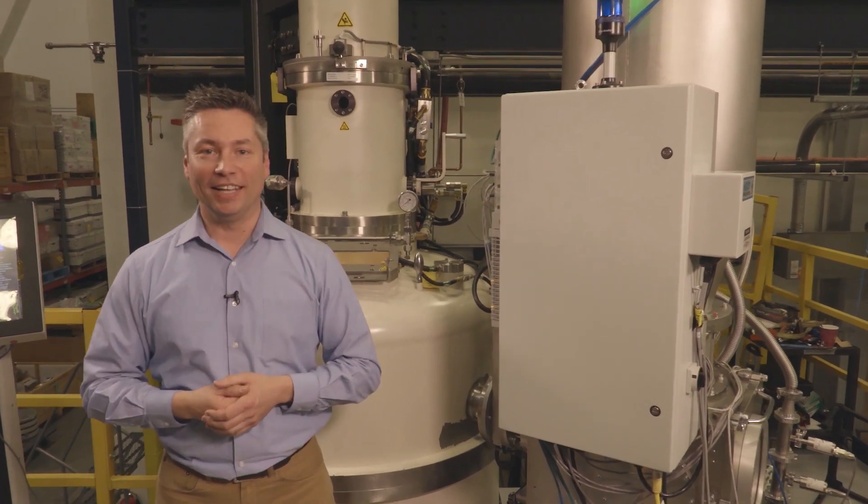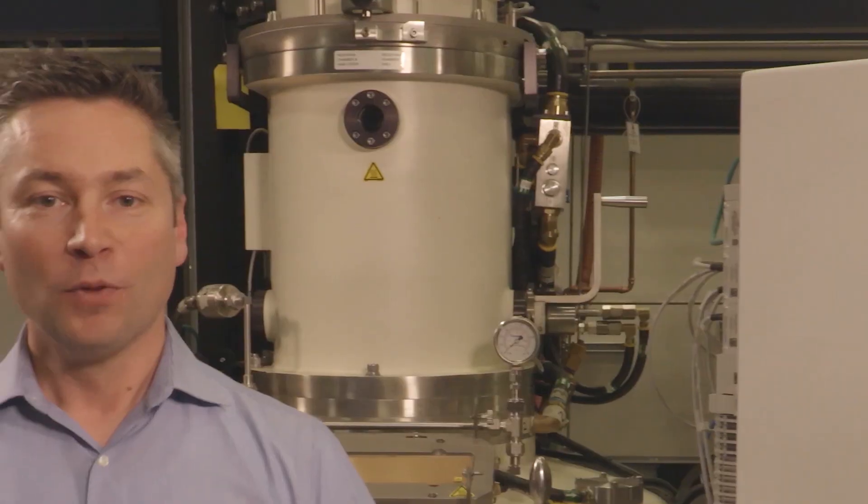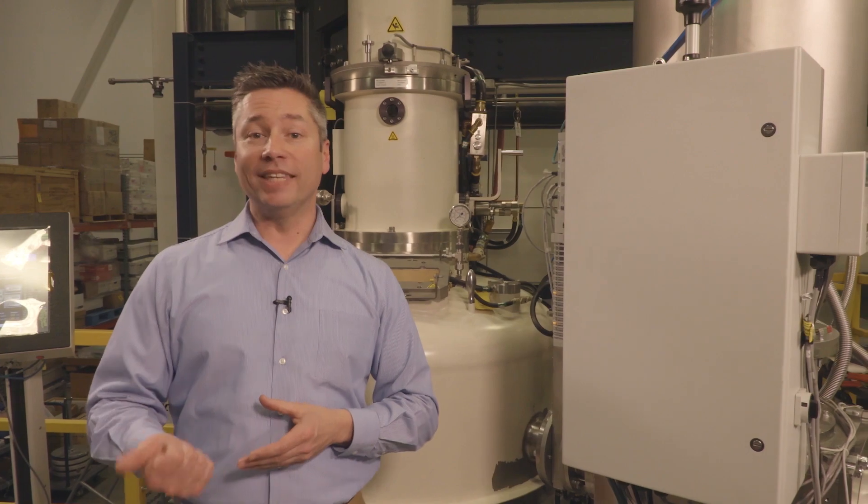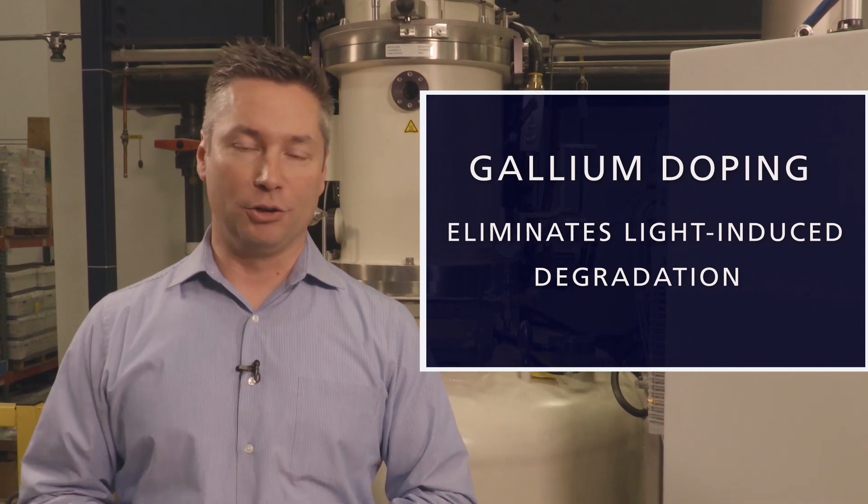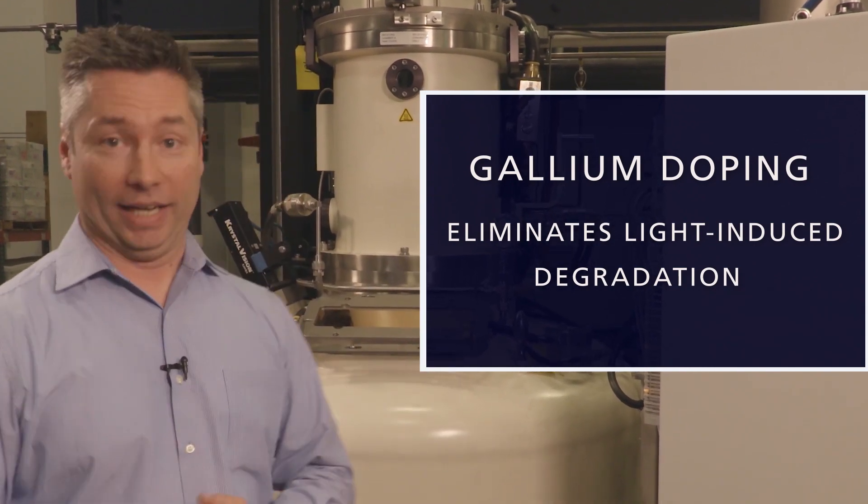Because of the uniform resistivity we're seeing in our ingots, we're able to address one of the issues in the industry: light-induced degradation. We're able to dope with gallium continuously with our feed, and that allows us to eliminate the light-induced degradation in our ingots.